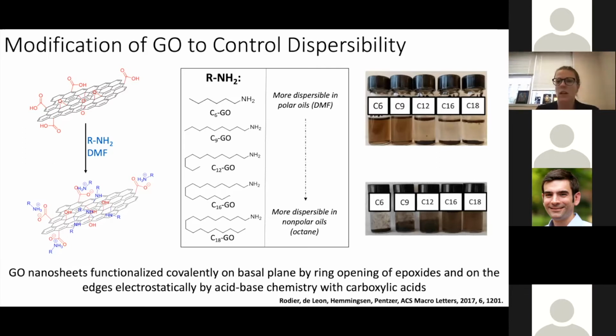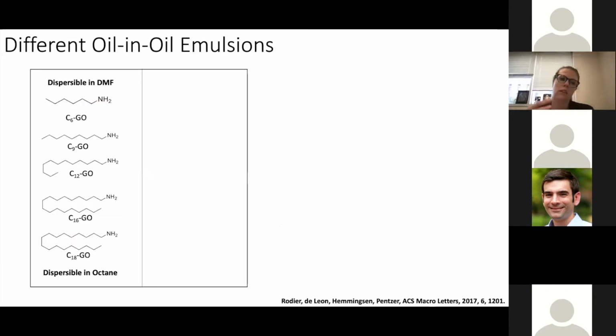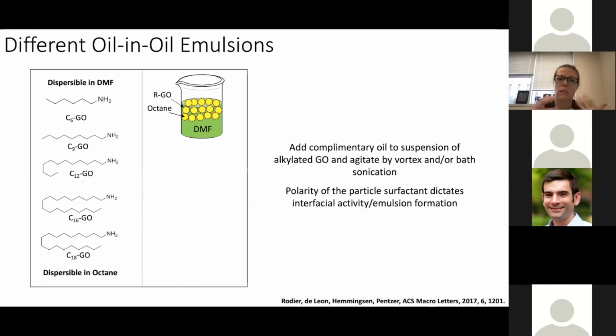And I should say, with the bottom right here, these longer chain alkylamine modified nanosheets, they do precipitate out after 2 hours, but they're dispersible for long enough in order to make the emulsions. And so if we consider that the continuous phase of the emulsion that we make is the solvent that the nanosheets are dispersible in, we could consider taking nanosheets dispersible in DMF, adding octane and agitating, and we then access droplets of octane in DMF. Alternatively, if the nanosheets are dispersible in octane, we could add DMF, agitate, and then get droplets of DMF in a continuous phase of octane, as long as the nanosheets have suitable interfacial activity.